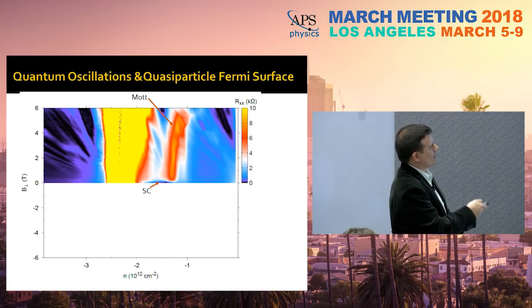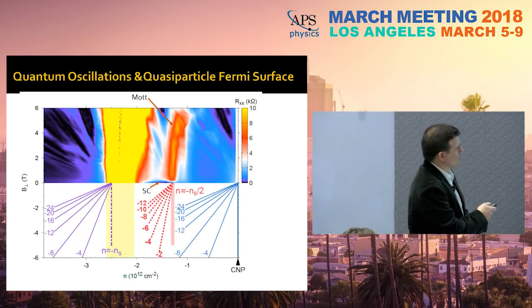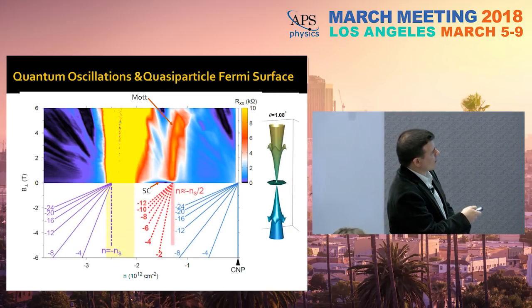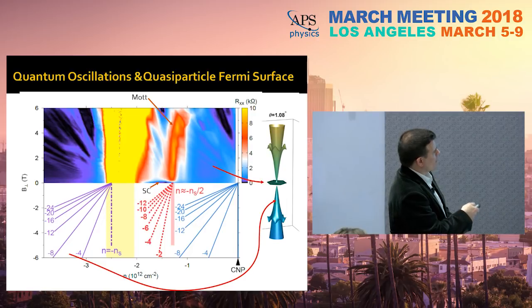And you see that there are several Landau fan diagrams coming out of different regions in this sample, okay? So this fan diagram and this fan diagram, these 2 fan diagrams. The contrast is optimized for this. These are actually very beautiful fan diagrams, but we've optimized for this, which is the most interesting region. This fan diagram comes from the sort of Dirac points of this flat pancake. This one comes from this highly dispersive band, so this has very high mobility, highly dispersive band.